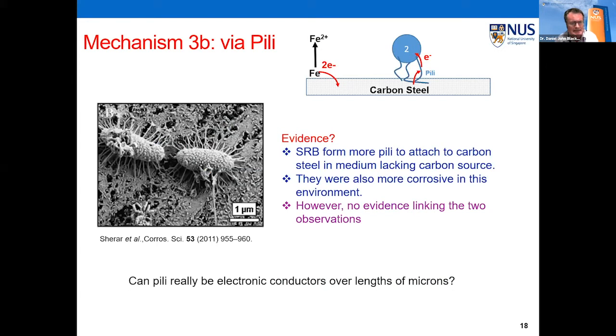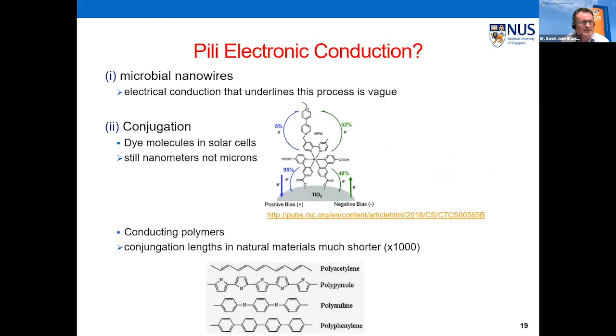And then there's these pili. Okay, SRB do seem to form pili when attached to carbon steel, and they're a more corrosive environment. But just because you see them in that corrosive environment doesn't really mean that the two are linked, right? There's no cause and effect being established. So if you start thinking, can pili really be electronic conductors over the lengths of microns, then you have to think, okay, what's the mechanism? In papers, you'll see electrical conduction via microbial nanowires, but that's rather vague.